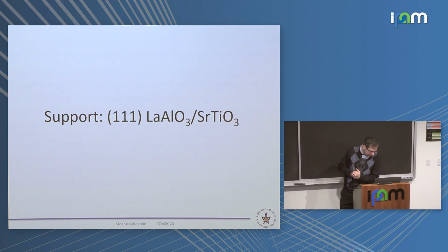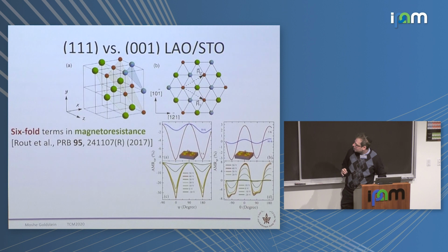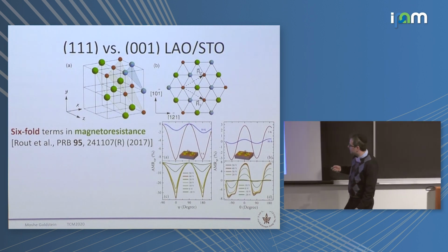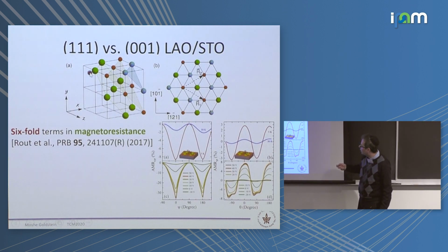So my colleagues are also able to make the 1-1-1 interface. Somehow this is harder to do, so not many groups can do that. That just means that you cut STO along the 1, 1, 1 direction in this way, and you grow LAO in this way. And then actually, when you look at it, it's a cubic crystal, but you cut along this direction, you have hexagonal symmetry.